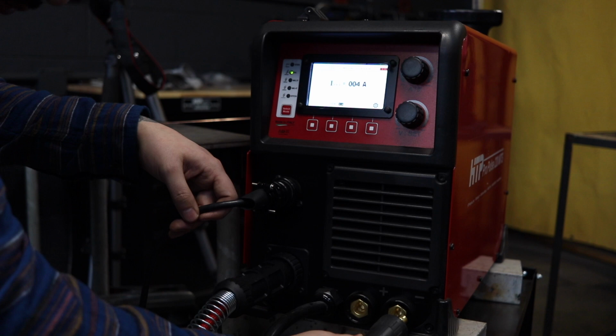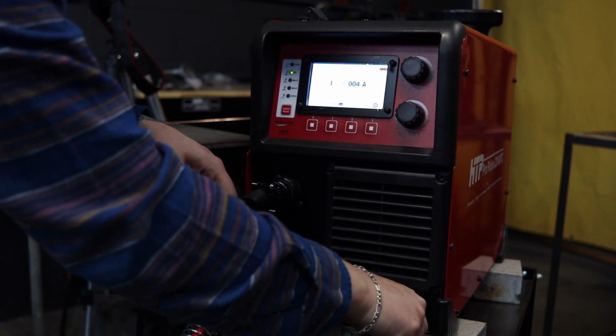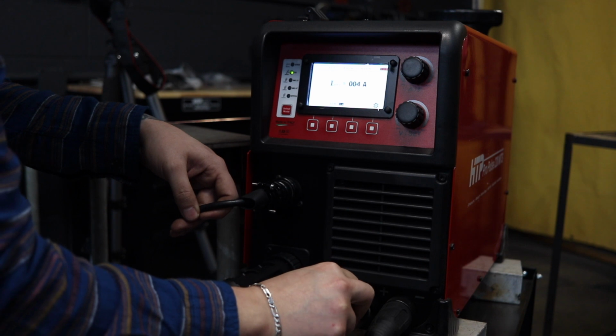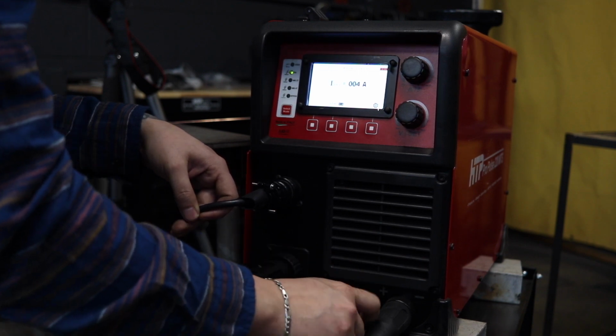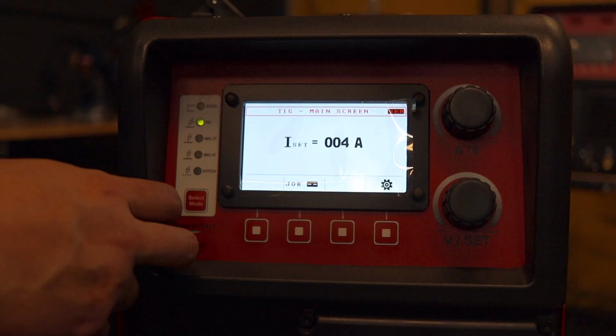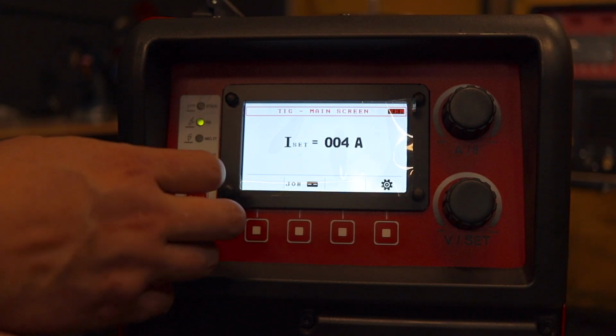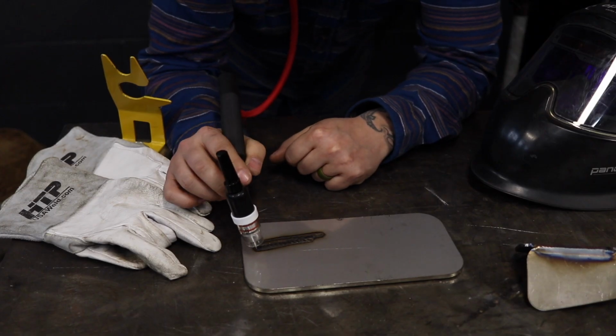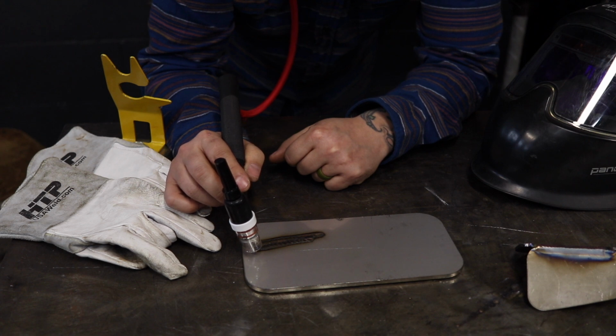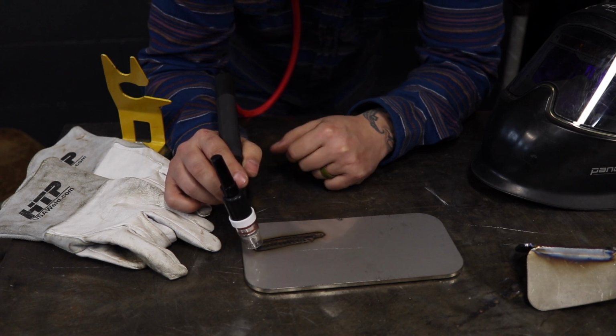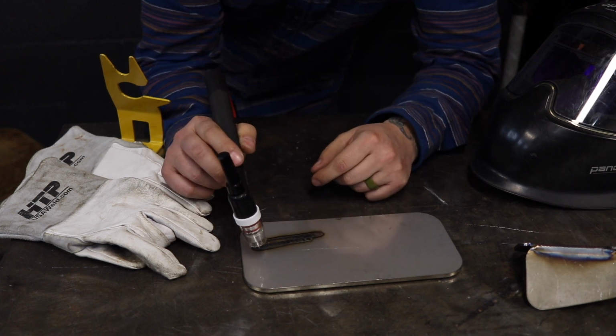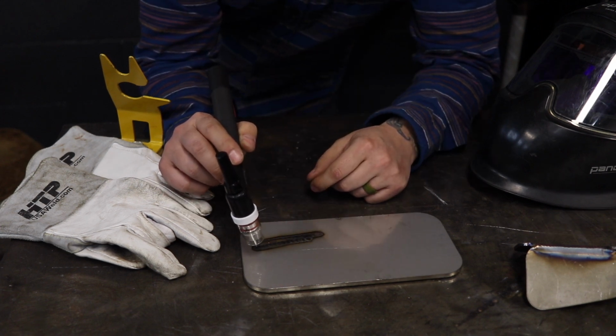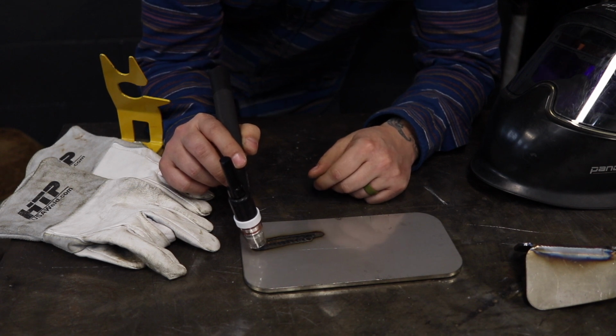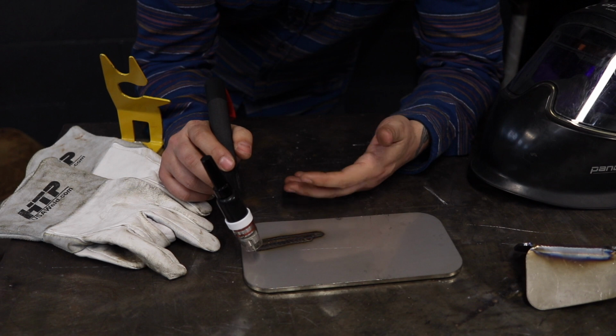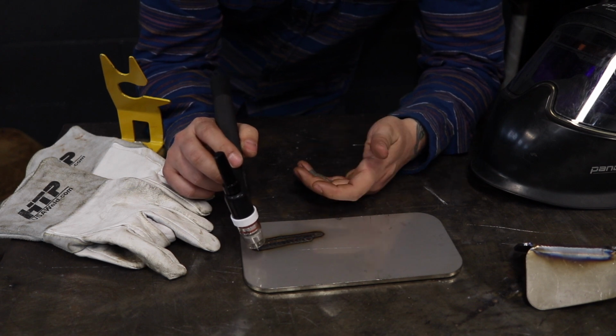Now we are going to put your pigtail in the negative receptacle, and your ground clamp will now be in positive because we are in direct current electrode negative. This machine is not equipped with a high frequency, so this will be a DC lift arc ignition. Basically what that means is you touch the tungsten to the material, press on the pedal, and once you lift, it will create the arc. Also with this machine, the power source itself is direct current, so you will not be able to TIG weld aluminum with this machine. To TIG weld aluminum, you're going to need alternating current, or AC.